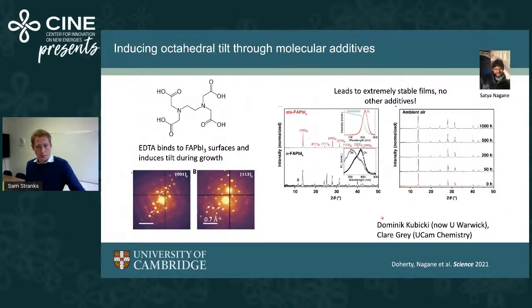And just to give one example where we're trying to not use these other tilt-inducing cations, we're actually using other additive molecules to make the pure formamidinium lead iodide tilted without needing cesium or without needing methylammonium. This is an example where we use EDTA, and we really quite nicely template growth of a tilted structure, this tilted formamidinium lead iodide structure. We see it's tilted from these, again, superstructure peaks in the scanning electron diffraction.